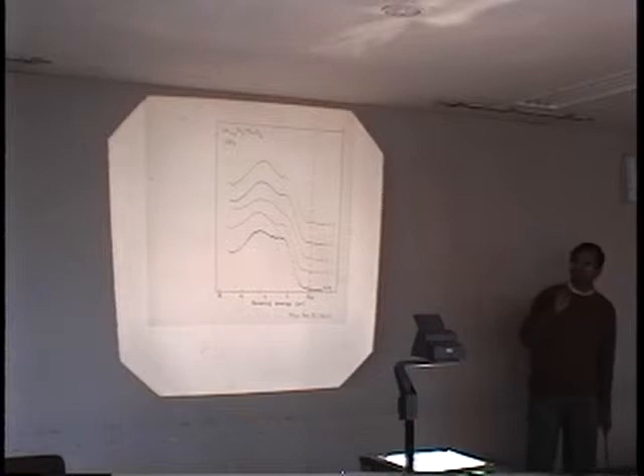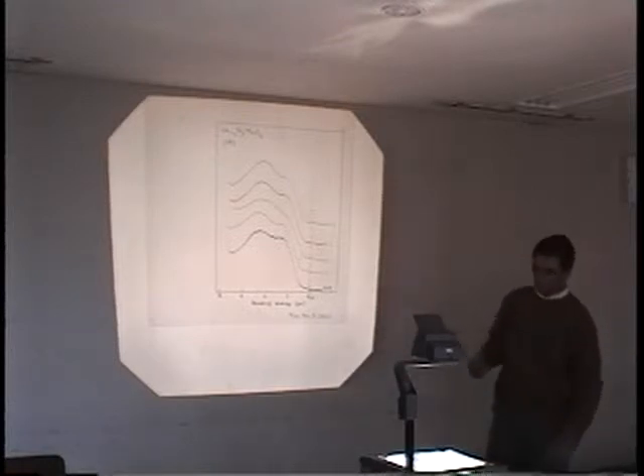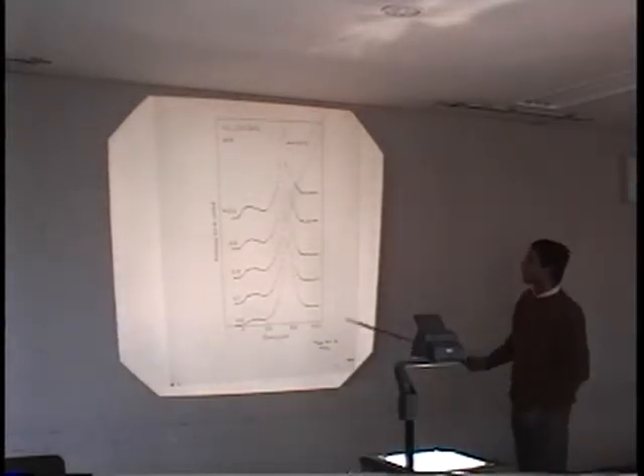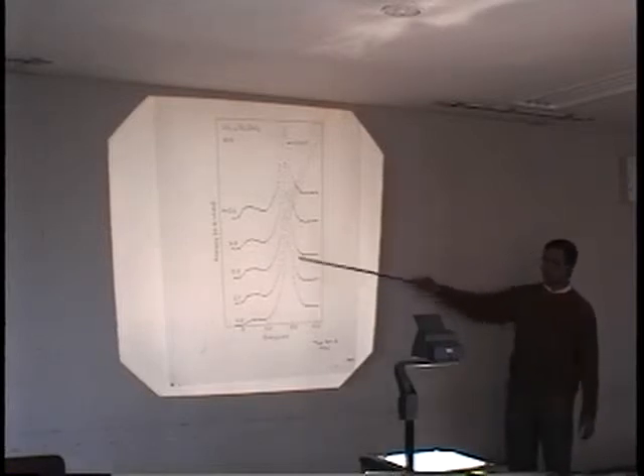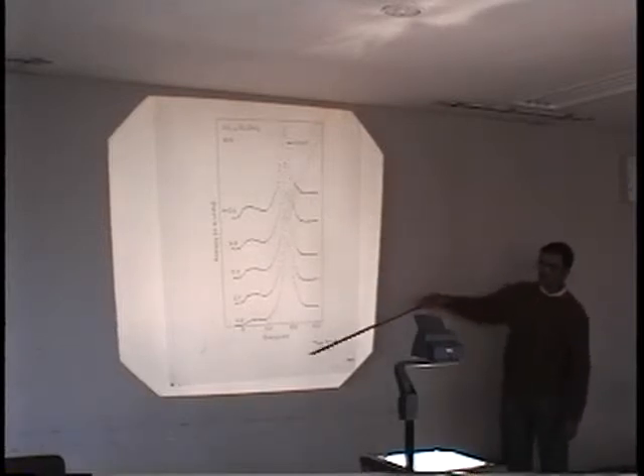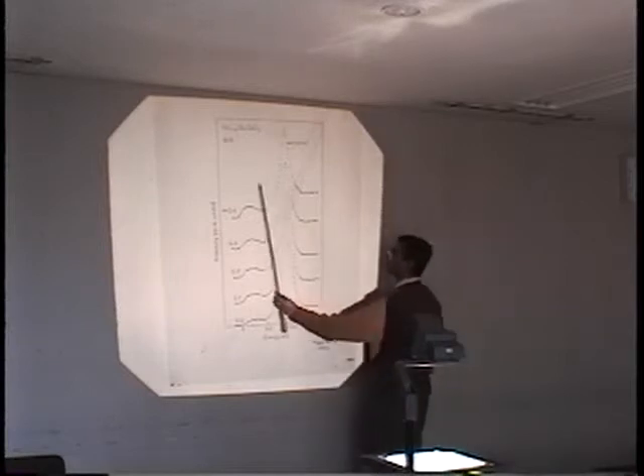One could of course say, look, what you're doing is doping holes. You're not doping electrons. So if you're doping holes, the best place to look for it is in the unoccupied part of the spectrum, not in the occupied part, because hole doped states will show up more strongly in the unoccupied part, and that's true. So if you look at, for example, the lanthanum strontium cobaltate system, once again apply the same theorem. This is the intense peak, so we are not interested in this region, right? Because any intense peak is uninteresting to the spectroscopist.